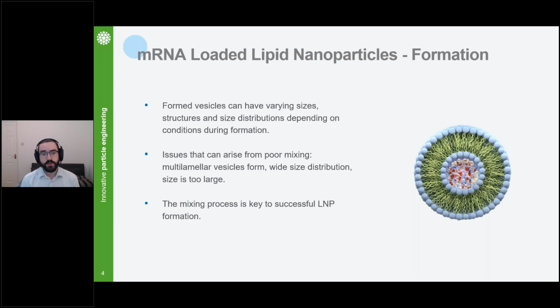Additionally, a lot of these processes are terminally sterilized via sterile filtration. So trying to pass materials in the nanoscale with wide size distributions through a sterile filter can result in significant losses if you have quite a wide size distribution. And that's the issue with some of them being too large, as you have very heavy losses. And when you've just spent millions of pounds synthesizing your RNA, the last thing you want to do is lose it on a filter right at the end. So the mixing process is absolutely the key to successfully forming these particles.